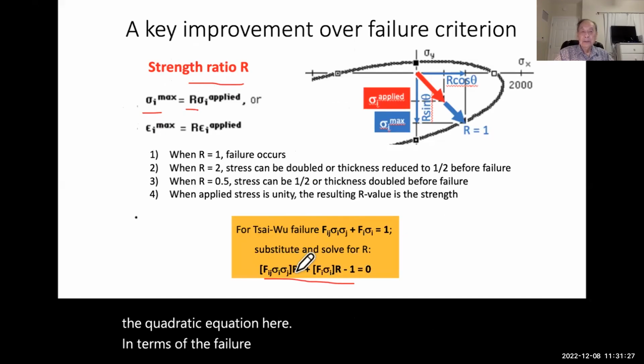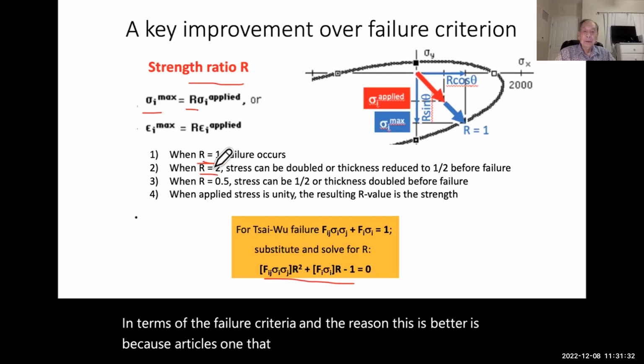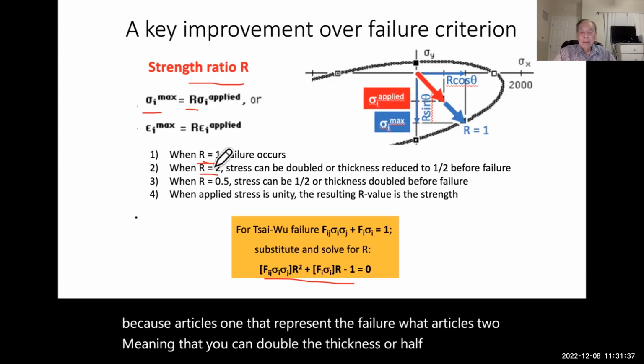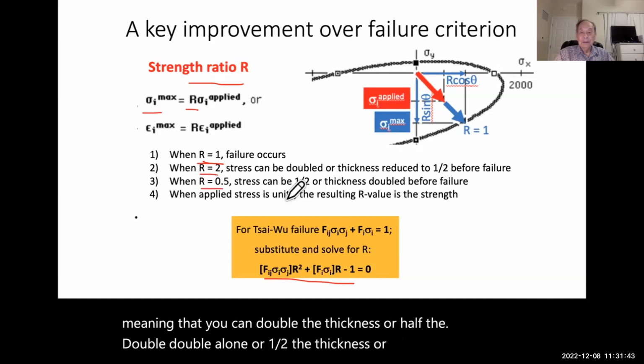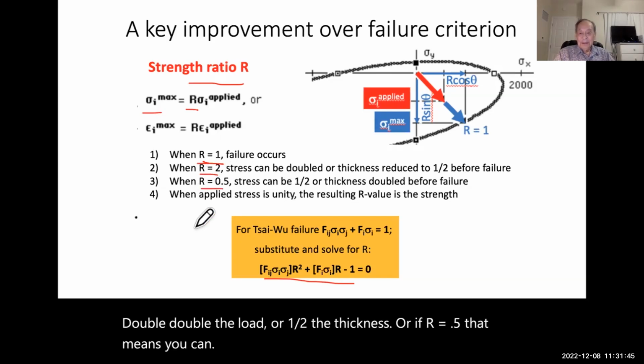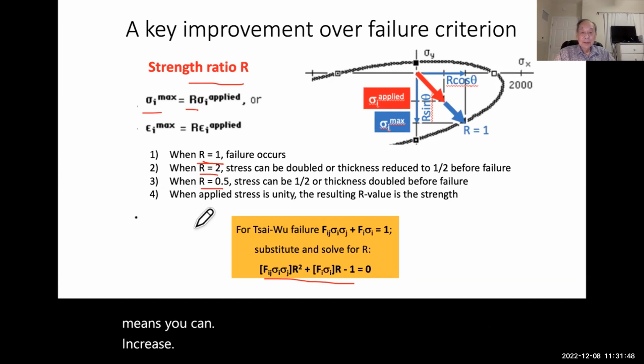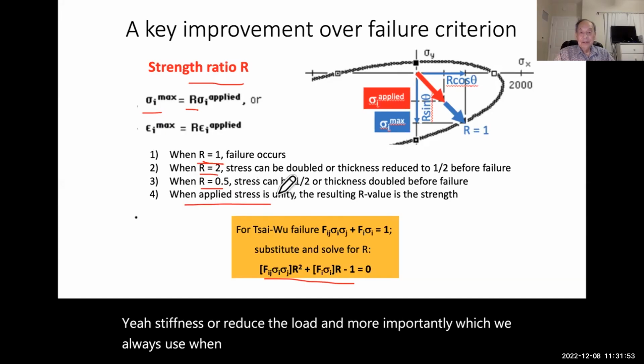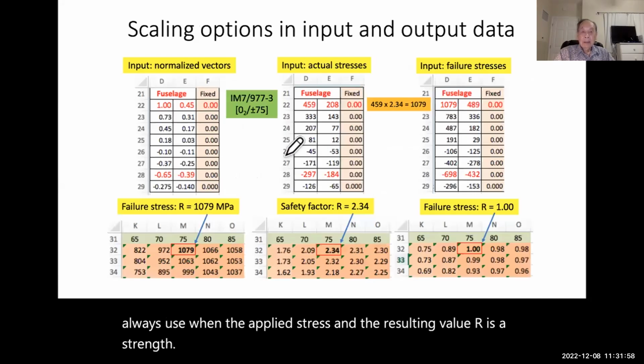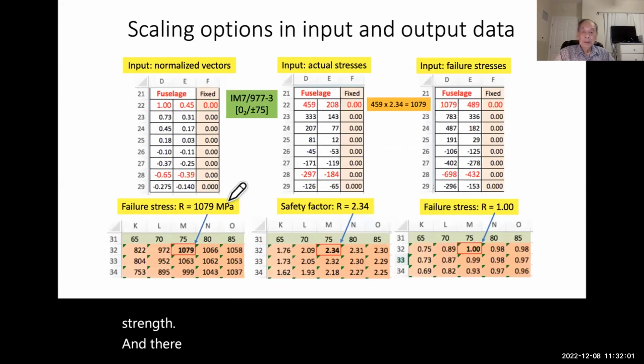And the reason this is better is because R equals 1 represents the failure, while R equals 2 means that you can double the load or halve the thickness, or if R equals 0.5, that means you can increase the stiffness or reduce the load. And more importantly, which we always use, when the applied stress is unity, the resulting value R is a strength. And these are the conditions showing what the various R values could mean.